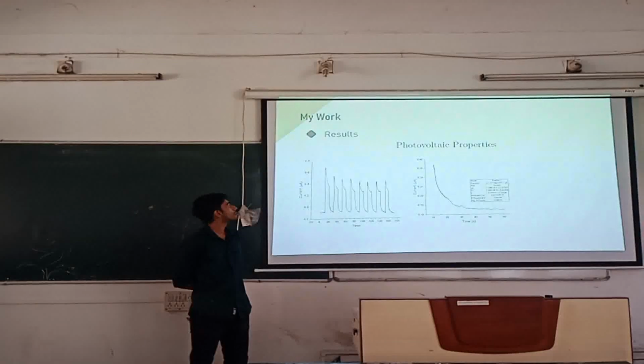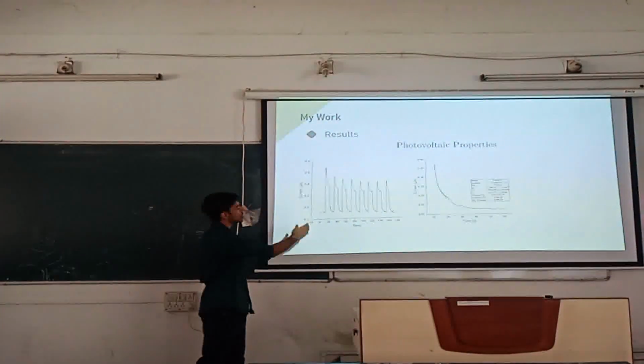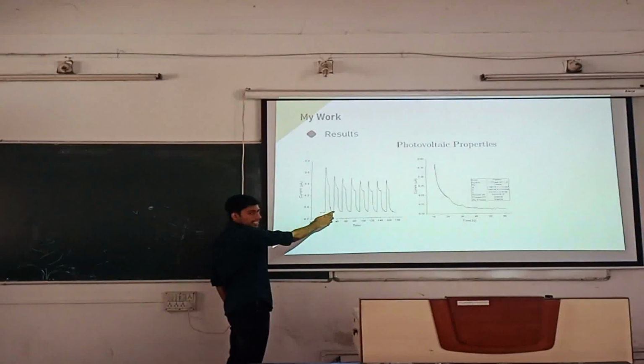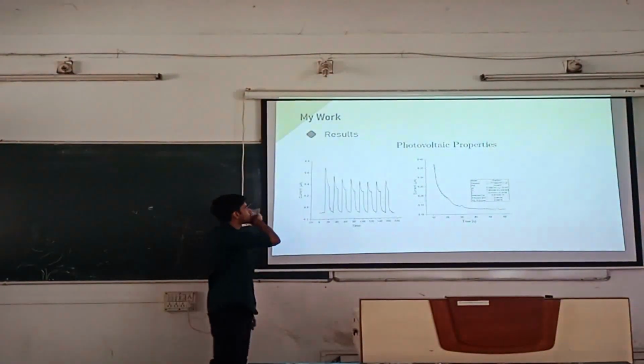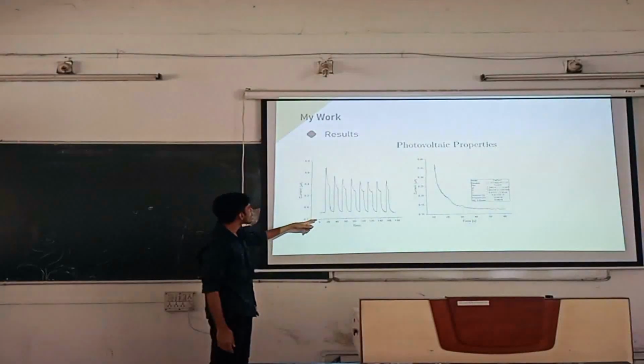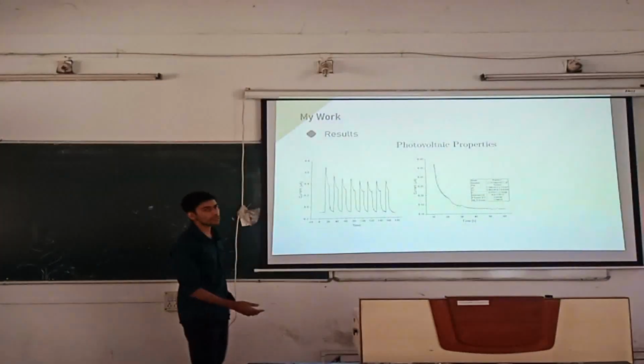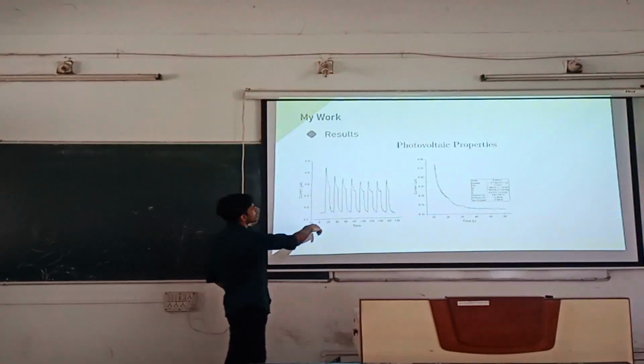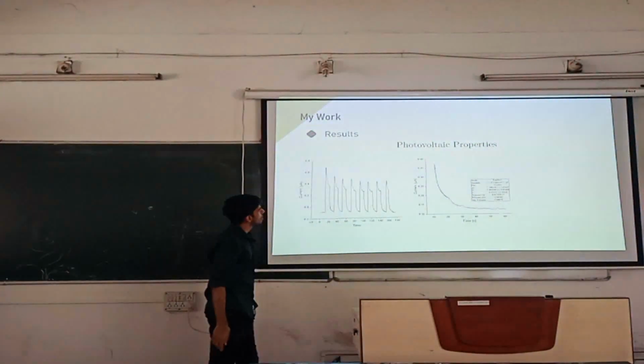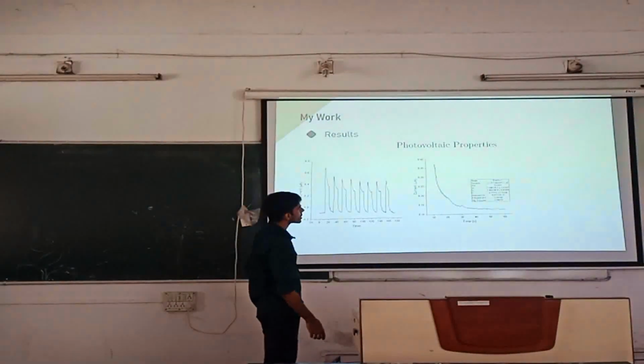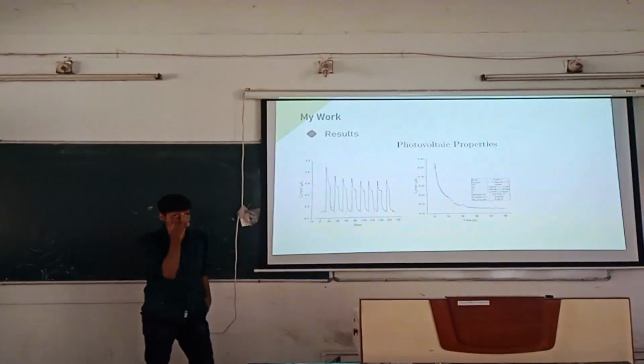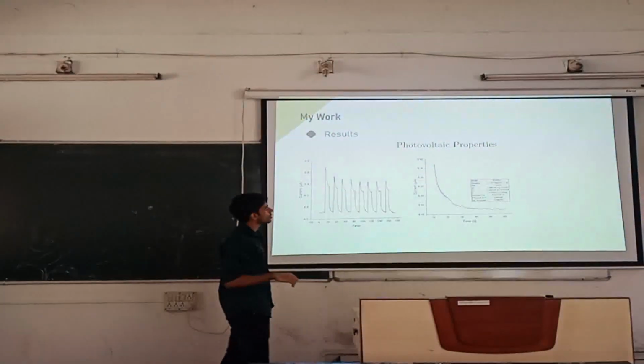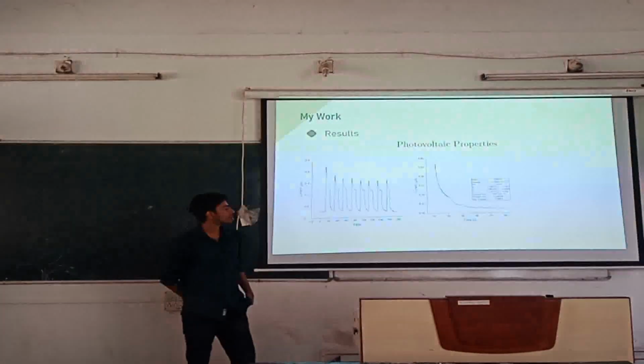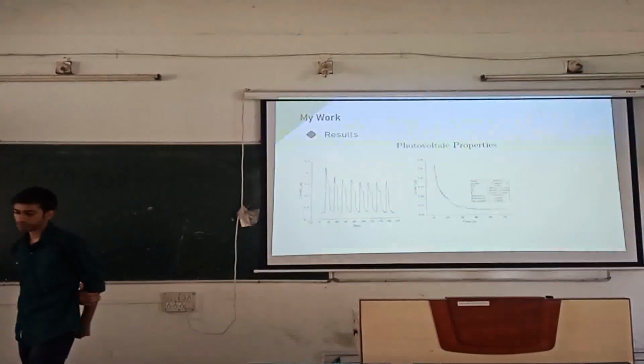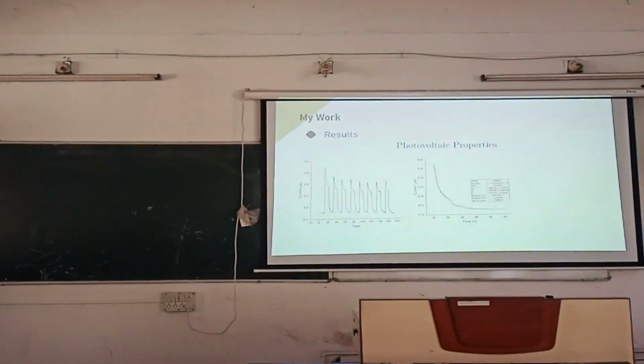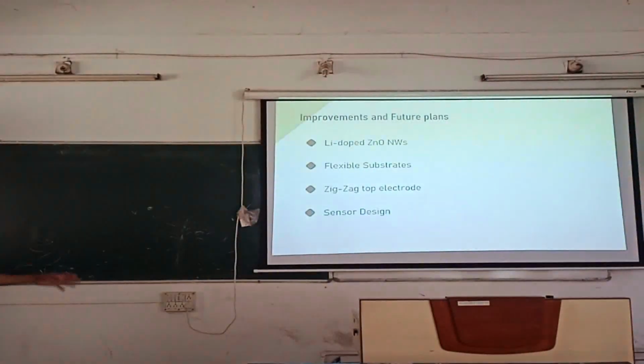So we just did a test where we exposed our crystal to sunlight in 20-second intervals, and each time we exposed it to sunlight, we got about 0.6 microamps of current, a sudden burst of current. Then it decayed and saturated to almost 0.15 microamps. So we were getting a short circuit current of 0.6 microamps from the zinc oxide nanowires. Yeah, and that's it. This was all I have done till now.